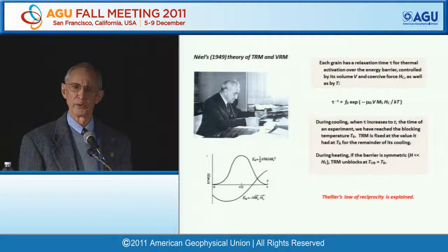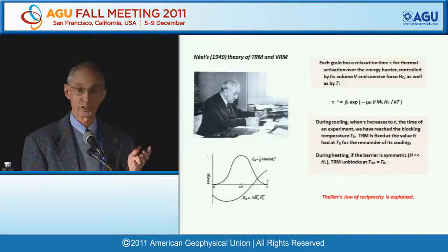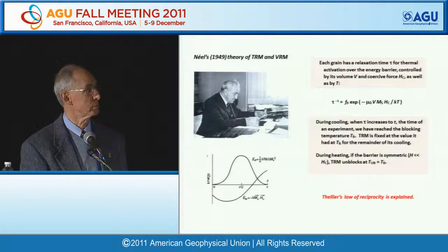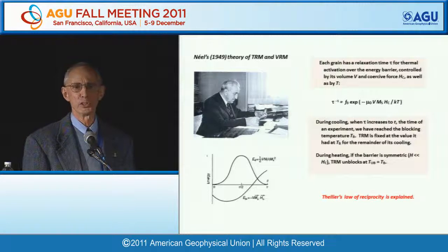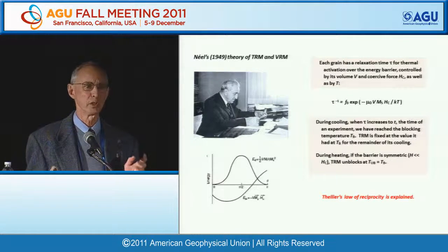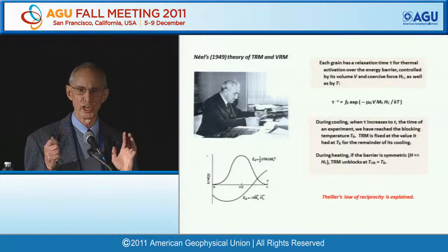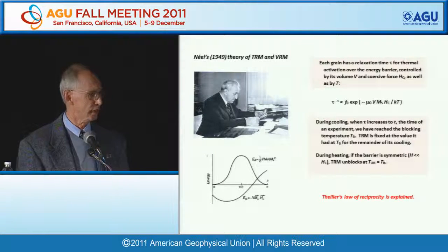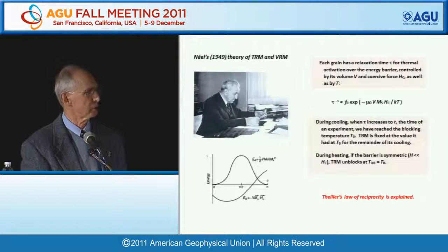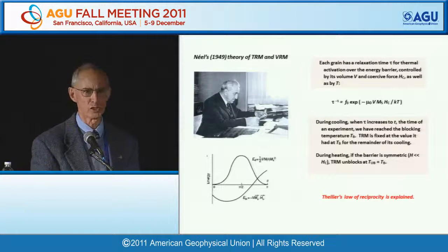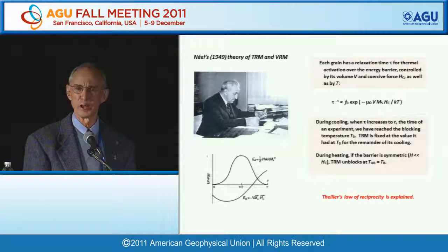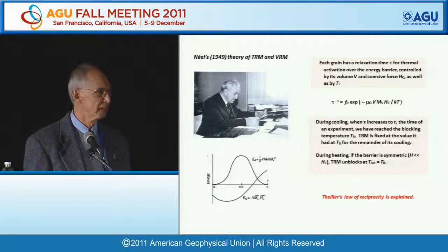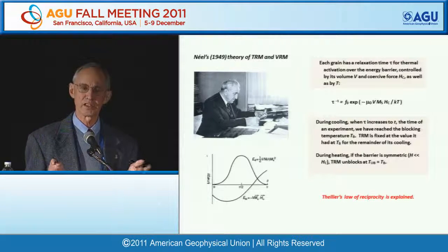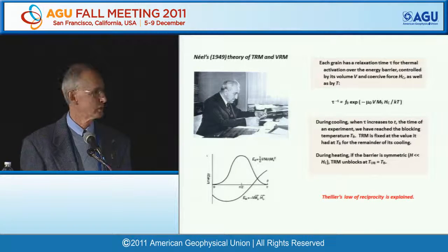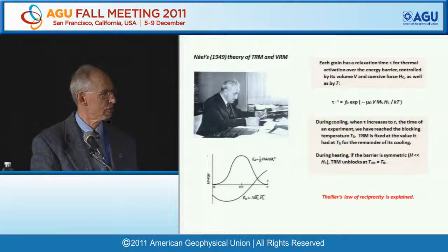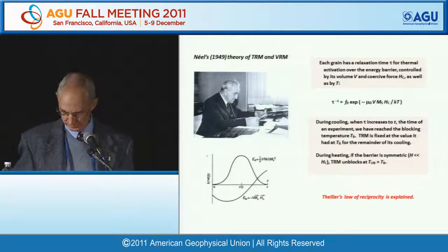So during cooling, when the relaxation time increases, which it does very rapidly because of the exponential function, when you reach a relaxation time that's equal to the time of your experiment, TRM is blocked in very permanently. That's the blocking temperature. If you later demagnetize by heating up in zero field, then the grain will demagnetize at exactly the same unblocking temperature. So there is Thellier's law of reciprocity explained.